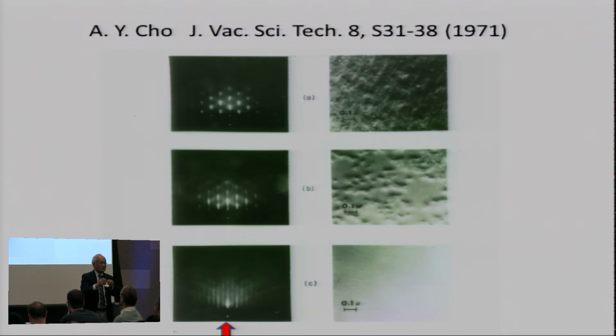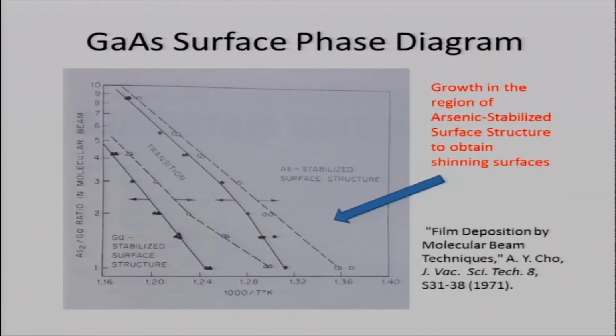That shows the atom in the 110 azimuthal is 2 times larger than the bulk crystal in real space. So with that, I found out if you use different arsenic to gallium ratios and different substrate temperatures, I therefore plot the arsenic to gallium ratio on the vertical scale and 1,000 over degree K on the horizontal scale. I plot the arsenic stabilized surface structure and then the gallium stabilized surface structure on the left-hand corner.